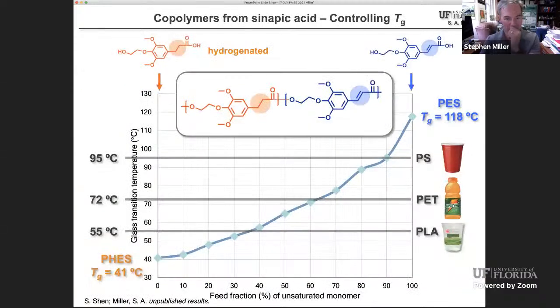What else can we do with this? Well, depending on the extent of hydrogenation of the double bond. Nature gives you the double bond in the back, in that part of the sinapic acid. But if you hydrogenate it through standard methods, you can tune the glass transition temperature. If we have a fully hydrogenated version of this, shown here by this orange repeat unit, you get a glass transition temperature for this poly(hydroxyethyl sinapate) of about 41 degrees.